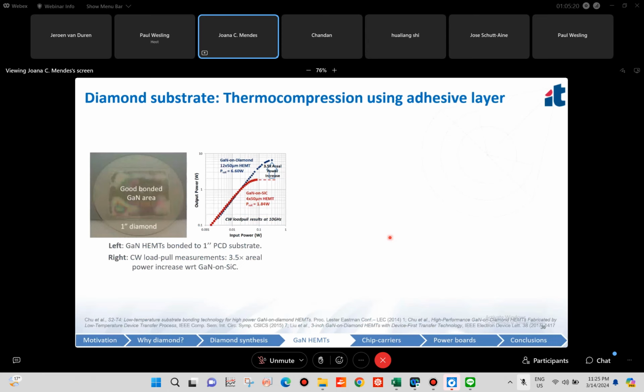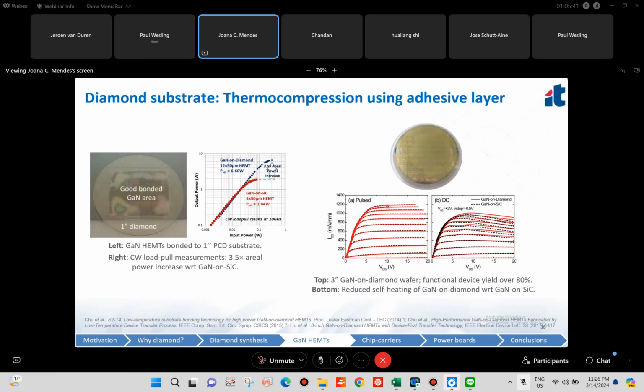And here you see one of the first published results where the gallium nitride wafer was bonded to a 1-inch PCD diamond wafer, allowing for a 3.5 times areal power increase with respect to GaN on silicon carbide. And here you see a 3-inch GaN on diamond wafer with a functional device yield over 80%.